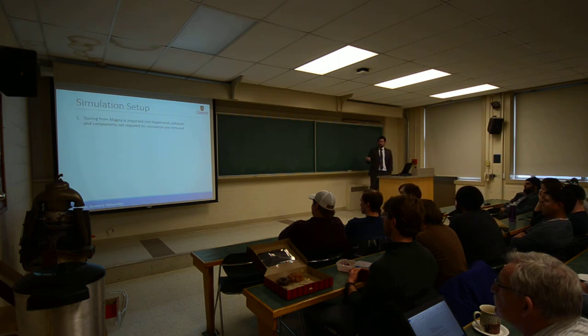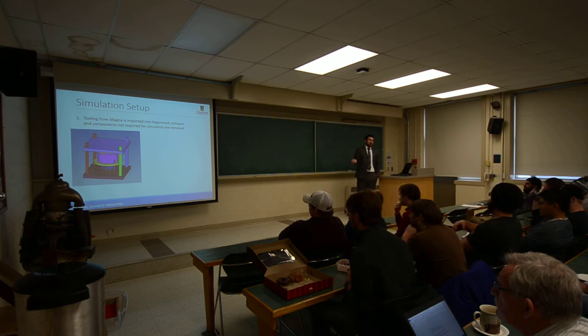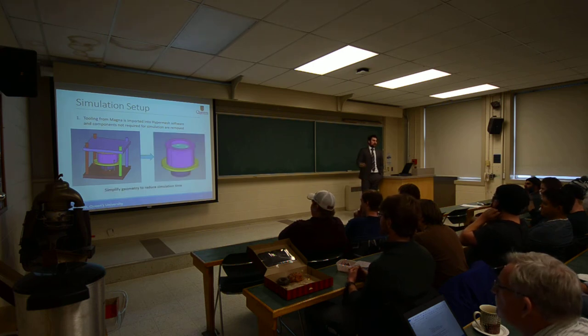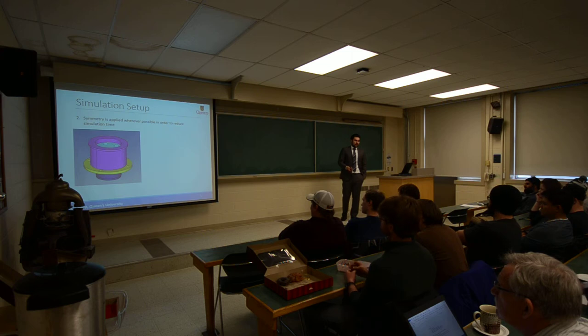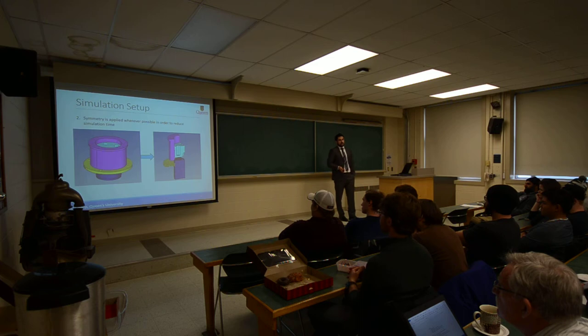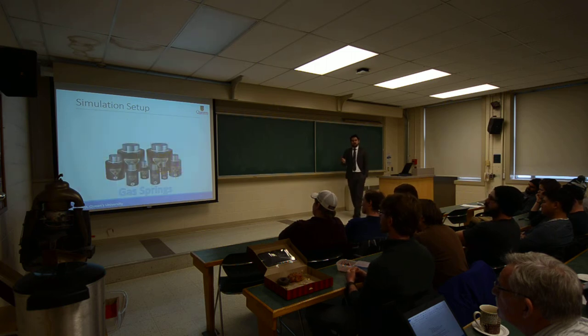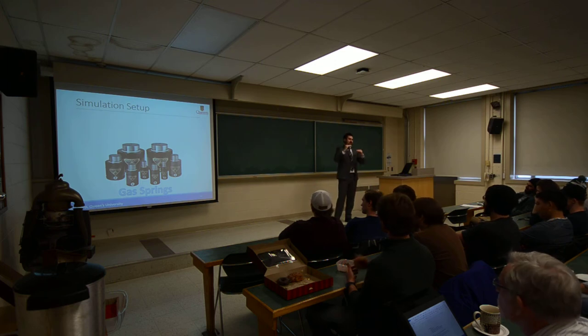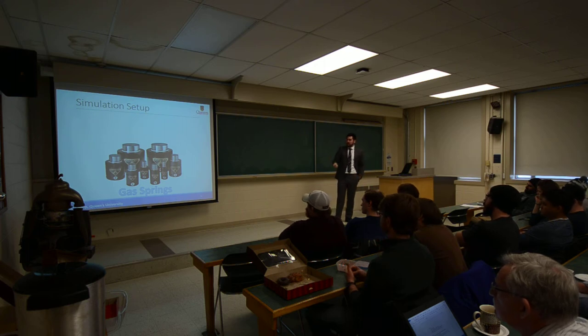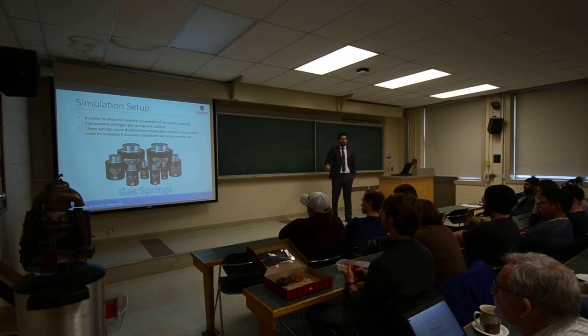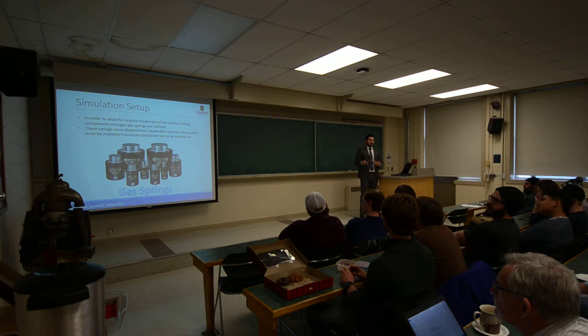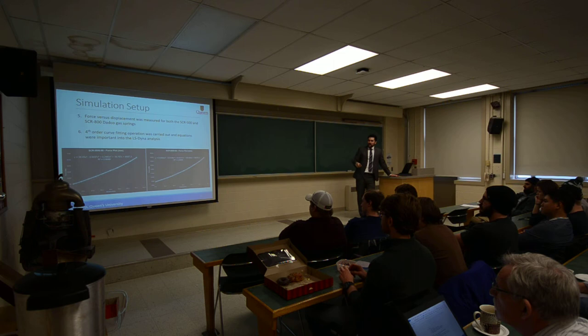We get our tooling geometry from Magna as CAD, which has everything needed to construct the tool. Because we're doing a numerical solution, we can constrain degrees of freedom and remove unnecessary parts. We can also use symmetry constraints — this model has quarter symmetry, allowing us to eliminate 75% of the model with no effect on accuracy. We then mesh the tool surfaces and add elements. We also need to model the relative movement created by die springs or nitrogen gas springs, which give displacement-dependent reaction forces. I took the two gas spring models used for can forming, tested ten points, applied a fourth-order curve-fitting equation, and imported these into the simulation.